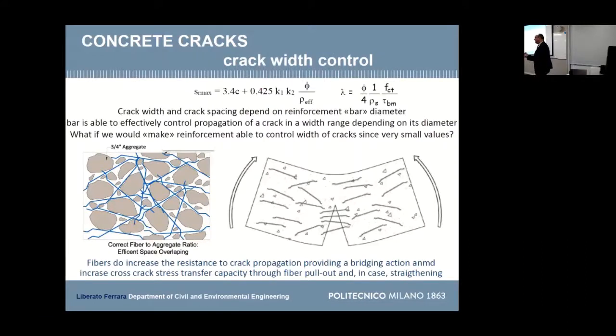So what is the idea behind the ultra-high performance concrete process? We have seen that concrete cracks and the crack width is proportional to the bar diameter. But if you think of a bar, the smallest commercial diameter cannot go below a certain threshold, because it still has to comply with some ductility requirements and so on. If you look for ductile steel, the smallest available diameter you find on the market is 8 millimeters, more or less. So what shall we do if we want lower and lower reinforcement bar diameter?